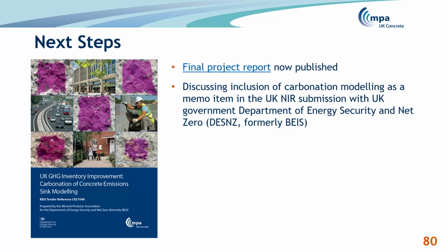It's a pragmatic calculation, and certainly, for the building prototypes that I showed you very quickly, we counted also carbonation on the piles, which is much lower than the carbonation in the superstructure because they're in the ground, and part of the piles we assume will be below the groundwater level. So there is much less carbonation under those conditions.